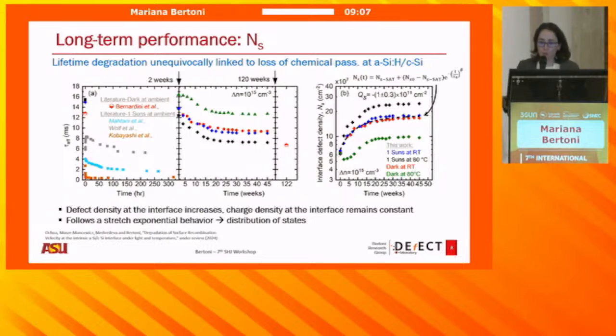Let's forget about the dark, because the dark is not the dark, but you get this particular response that follows a stretch exponential behavior, which has the signature of a distribution of states, right? A distribution of transformations. And you can very well fit this curve, which is the interface defect density, with a stretch exponential behavior like this.